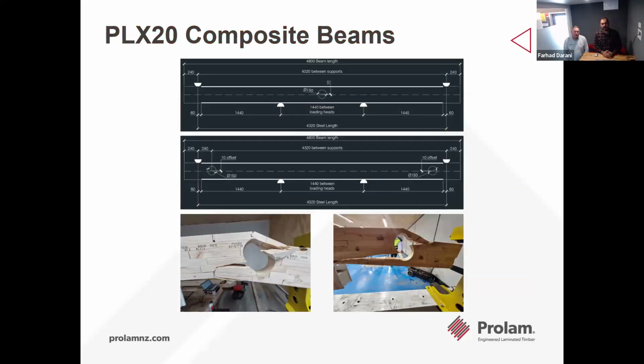So then we have done some other development tests, specifically, for example, for the services. There are some standard small holes through the beams that during the construction they have to make, but we have had queries from architects and builders on whether they are able to make bigger holes into the PLX20 beam, and we have done different tests. Actually, we have done a test with a 150 millimeter hole at the middle of the beam. So for this test, the performance was very good.